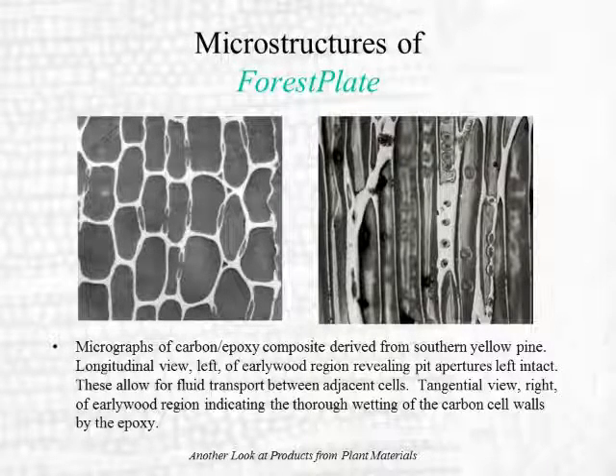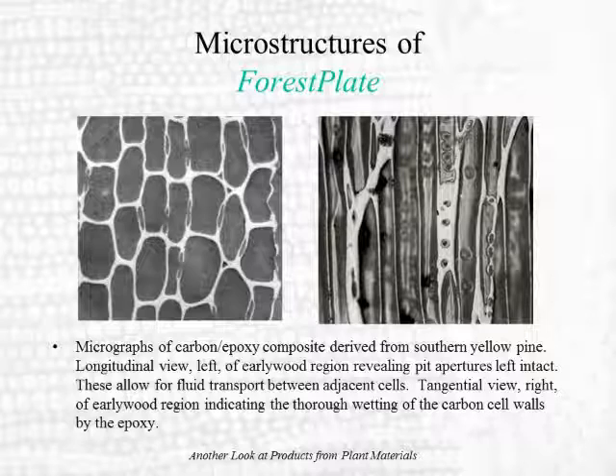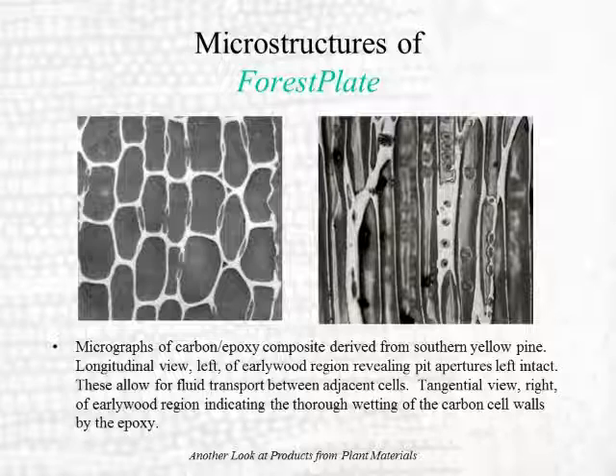It has all those anatomical features, the microstructure that's in wood. This is the lumen inside a cell with pit apertures between cells that in the wood allows fluids to transport between them. All those features retained. You see good wetting of the epoxy to the carbon, or the polymer to the carbon, and these are just two different views based off of whether you're looking along the longitudinal direction or along the tangential direction of the wood.